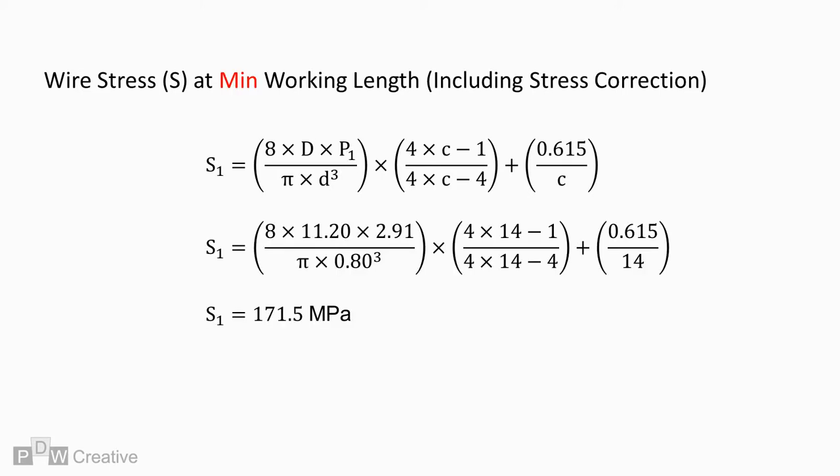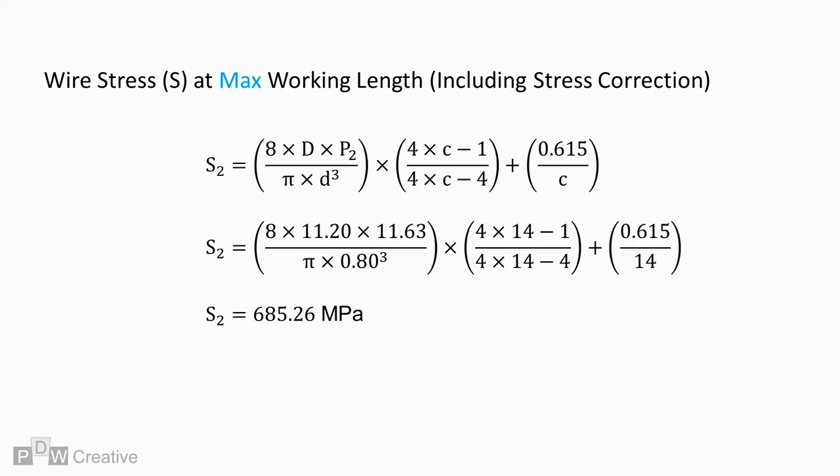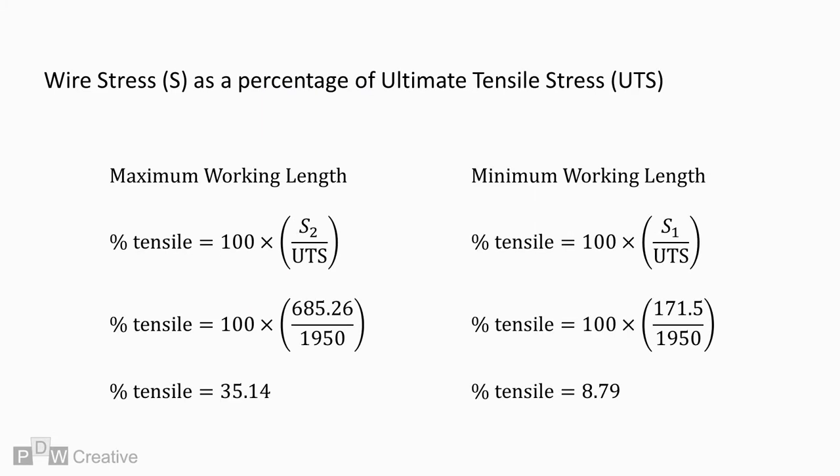Our min working length design stress works out as 171.5 megapascals, while our maximum working length design stress works out as 685.26 megapascals. At both working lengths, stress is below the target stress limit of 45% UTS. So for static loading applications, the spring is capable, but we need to investigate fatigue life before making a similar statement.